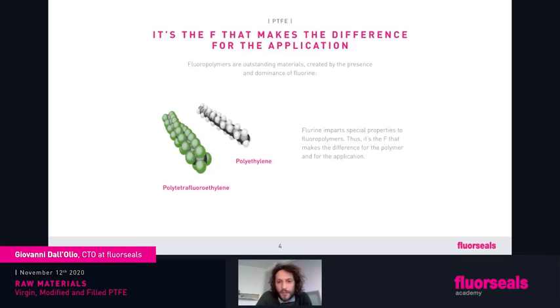Basically, you can think PTFE can withstand 300 degrees, 280 degrees. Polyethylene will melt, will degrade earlier. Why? Because temperature is energy. We have a strong bond and the protecting layer of fluorine. You give high energy. For example, we have two parts, one of PTFE, one of polyethylene. We put them in the oven at 200, 250 degrees. PTFE, nothing happens. Polyethylene will start to degrade. Why? Because the thermal energy in this case will be transmitted to the polymer. Polyethylene has a weaker bonding energy, and it will start to melt and then degrade. PTFE is very strong, and at temperatures up to 280 and 300 degrees, nothing happens to PTFE. So fluorine atoms are the key of PTFE.